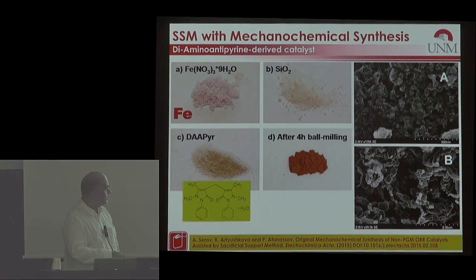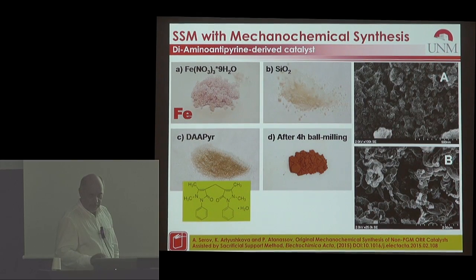We also make this catalyst, I don't know where this slide came from, but let me skip it. We make this catalyst also by ball milling. We don't need to do weighing. Ball milling allows us to put together all the materials: the silica, the iron precursor, the nitrogen-carbon precursor. But see what's happening. When you do ball milling, you start a chemical transformation. Because all these components are actually white powders, and after 4 hours of ball milling, you already have something that is red. So this is just food for thought.